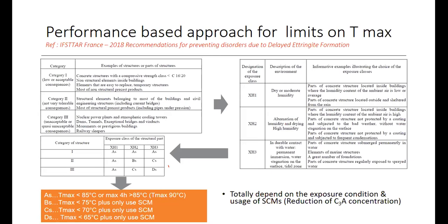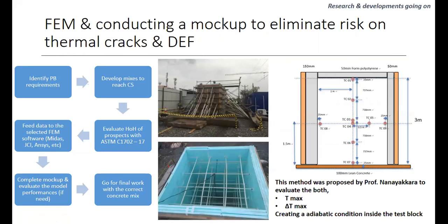The risk is very high when the concrete is exposed to moisture. I told you that with the presence of moisture, the delayed ettringite formation is expedited. So if we can reduce the moisture ingress, we can reduce delayed ettringite formation as well. If we refer to these standards, they have systematically and rationally categorized how we can control those temperature limits within the allowable range. For that, a very good mechanism has been developed.